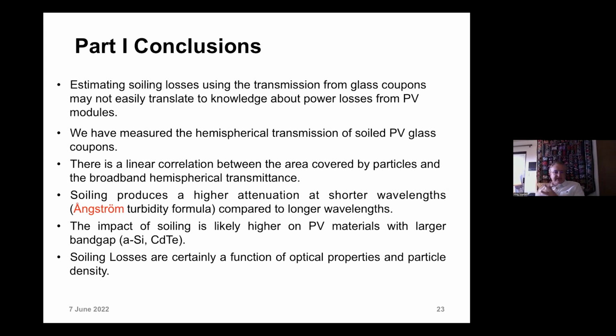And just like I showed you in the last slide, there's a linear correlation between the area covered by the particles and the broadband hemispherical transmission. We got that from the last slide when we looked at beta. I said beta is connected to the amount of soiling versus the average transmission, that we see that there's a linear correlation there. That makes sense, right? More particles means higher transmission losses, and we do see that. Soiling produces a characteristic shape, higher attenuation at shorter wavelengths. The Angstrom turbidity formula, if modified, can handle that, can talk to us about that.